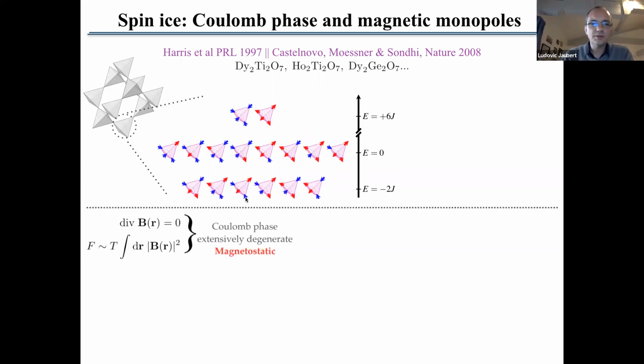In the ground state of spin ice, the magnetization is always conserved. All the magnetization flux that enters the tetrahedron exits the tetrahedron. It enters through the blue arrows and exits through the red ones, and it's the same for all of the states in the ground state. Because you have 6 different states in the ground state for one tetrahedron, when you pile up the whole pyrochlore lattice, you get an extensive degeneracy, and you get residual entropy even in the ground state.